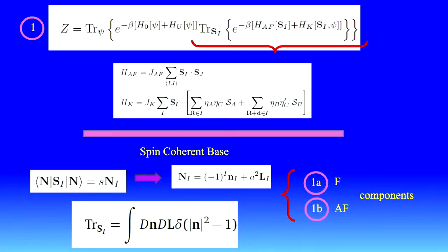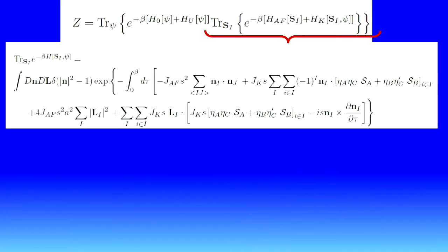So this is again a view. The partition function is the trace of this exponential, these two terms, and the expression in the brackets involves the two terms with localized spins. In order to calculate this trace, we use this spin coherent base where the expectation value of the localized spin is given by Ni, where Ni is a unit classical vector. And this Ni decomposes into an antiferromagnetic and a ferromagnetic component, in such a way that the trace is given by these two functional integrals. So just to summarize, this is the complete partition function.